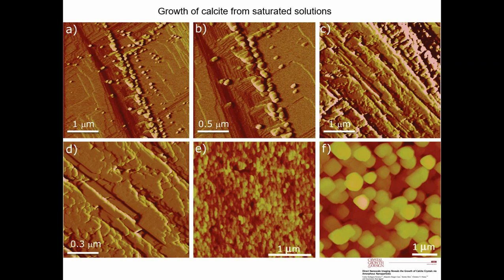I immediately get nanoparticles, but not all over the surface, only in particular orientations, and those orientations are along step edges, which are dissolving, or on etch pit sides. Image C is after a few hours, where those nanoparticles are merging along particular crystallographic directions, and then in D, a zoom in again, you can almost see the nanoparticles, but they're merging, getting straight lines, and straight lines always make us think we're undergoing crystallization.